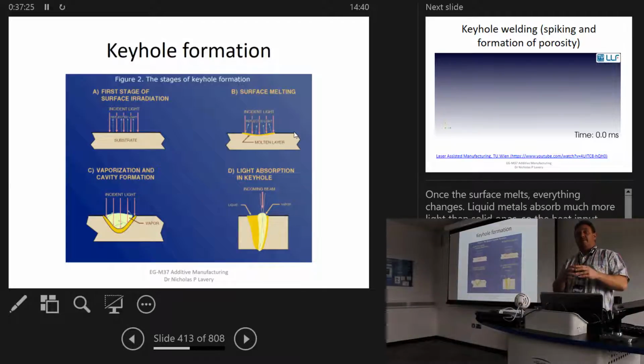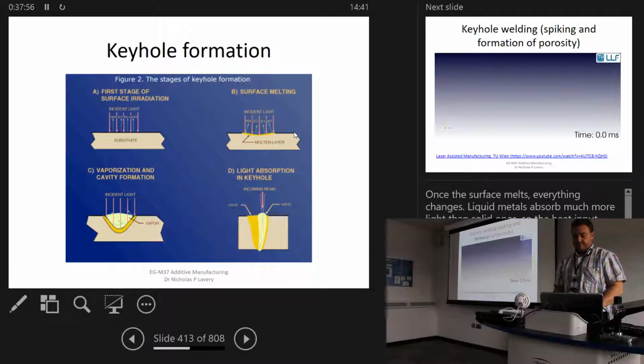But then that plasma that forms after it's vaporized actually acts almost like a lens. It takes in the radiation from the laser, reflects it into the hole, it comes back to it, and it's a sort of self-propagating effect. With the result that the plasma actually causes the melt pool to accelerate and bore into the material, which is why you end up with these rather tooth-like roots going deep into the material.